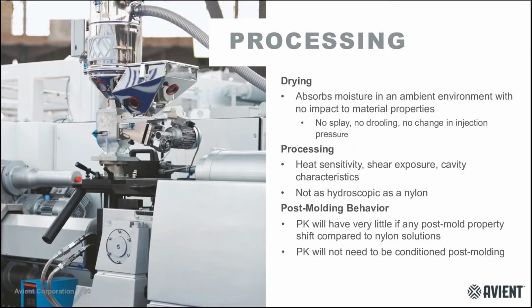When talking about drying, there's really no need to dry the material. It is not required, but it can be recommended for some of our solutions. And this is actually a positive for the material, because a lot of molders and suppliers tend to have issues with drying materials, as well as it just adds another factor into the mix. When you have to dry a material, you typically have to hit a certain threshold, or you get some kind of issues via processing. So having a material that is not going to pick up any moisture from ambient temperature and ambient environments is typically a benefit, and it helps to ease that process of getting the material through.